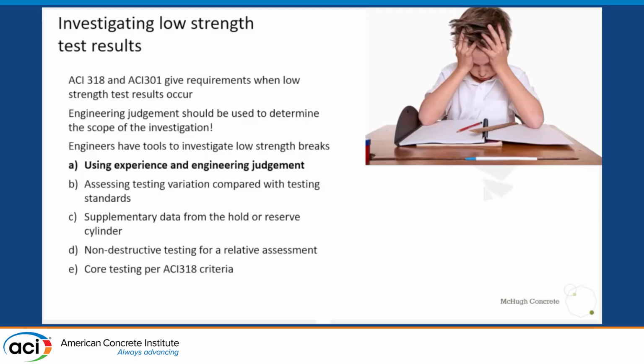And there's additional examining of the testing, so looking at the test reports, looking at any kind of information you can find, as simple as the trucks, the frequency of trucks, the temperature, all that kind of stuff, to see what kind of information can be gathered. Ideally, getting data from the hold or reserve cylinders, which would have been taken at the same time from the same batch, same truck, would be really helpful to understand what results we're looking at. Then non-destructive testing for a relative assessment, and last but not least, this is the worst case scenario, the coring.